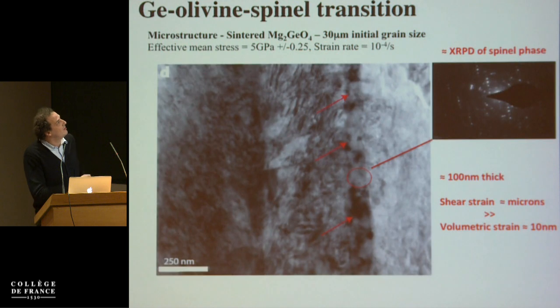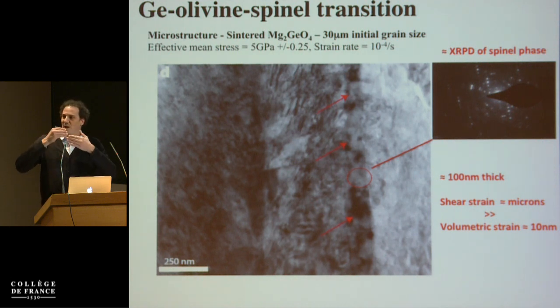If you do a FIB section along one of those lines, this is one olivine grain with some slip bands here and a large amount of dislocation. This is another olivine grain, and this is the fault. Now the fault is 100 nanometers across, and you see that the fault is made with this very fine grain here, and if you do the XRD on this grain, it is actually compatible at least with the spinel phase, and we know there is the spinel phase. So basically it's as if the fault was filled with the high pressure spinel phase. So inside the fault gouge is the high pressure spinel phase.